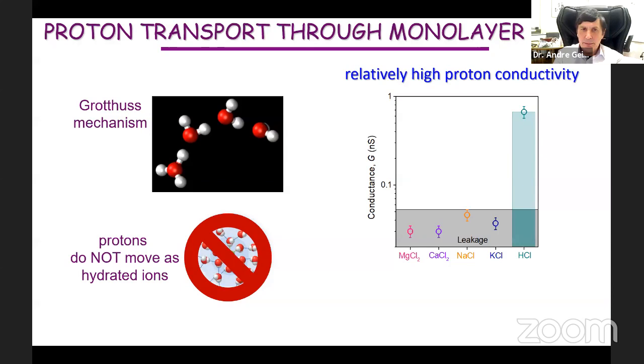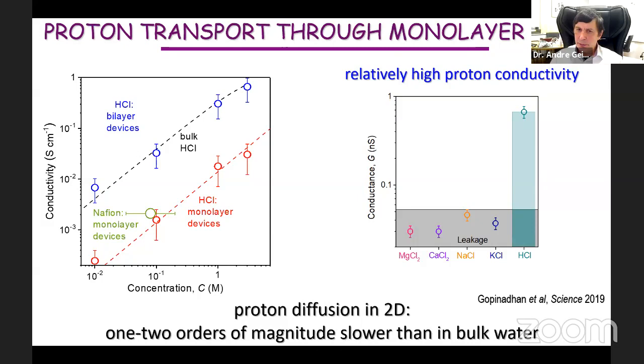Hydrogen ions travel by something called the Grotthuss mechanism. They exchange protons: this proton goes here, then here and here. So this is a mechanism which explains pretty well the proton conductivity of ultra pure water. So in this case, what we see is proton transport through. What is interesting is to find the absolute value of this proton diffusion, and we found out, I don't want to go into details, that it's extremely slow proton transport, much slower than in bulk water.